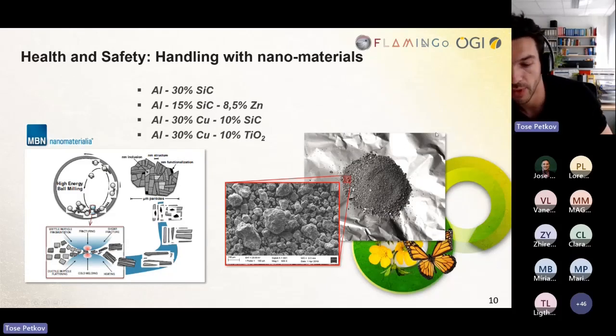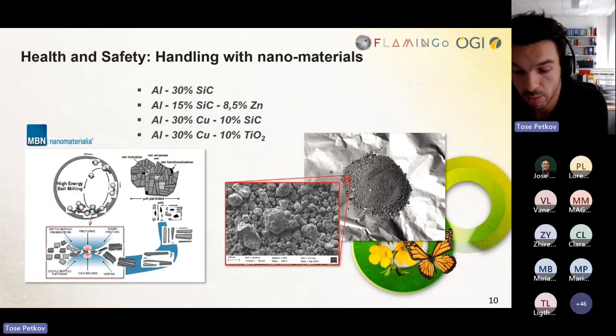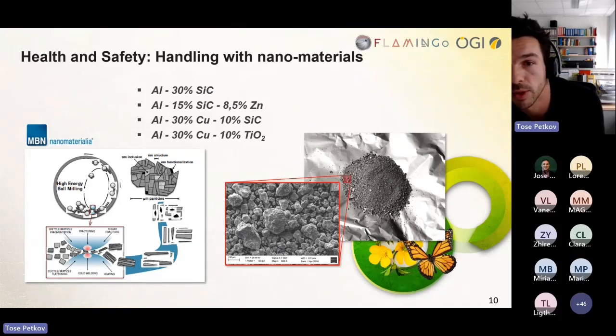So, a method to prevent working with pure nanoparticles is to disperse nanoparticles through solid-state processing methods such as mechanical alloying that allows production of homogeneous materials. Use a powder metallurgy approach. So MBN has the possibility to do this through high-energy milling, producing master batches that we use further in the foundry with different compositions and amounts of nanoparticles. Here you see, we tried aluminium with 30% of nano silicon carbide as nanoparticles, and also some combinations with zinc and copper, and also nanoparticles of titanium dioxide.